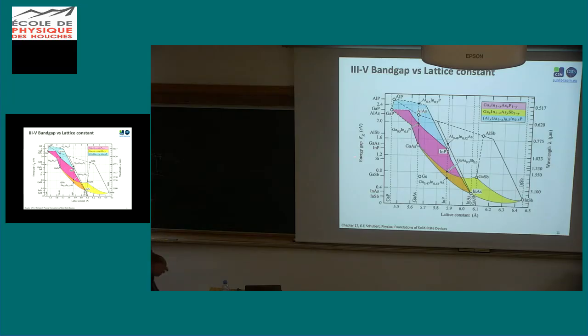Here you have on the y-axis the energy band gap of the alloy, and on the x-axis the lattice constant of the crystal you are growing. For example, if you look at gallium arsenide, it's very fortunate that whenever you are alloying with aluminum, you do not change basically the lattice constant of this crystal. And so it's a good platform to create heterojunctions or heterostructures in general. And this is one of the first couple of materials that were used, for example, for lasers.